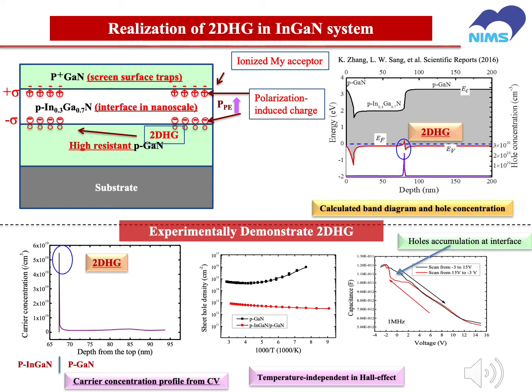But the two-dimensional electron gas is already utilized for HEMT device applications. The two-dimensional hole gas is very difficult to obtain. Here we use the InGaN/GaN heterojunction and successfully realized this two-dimensional hole gas from the band bending. From the CV characteristic, we estimate the carrier concentration dependent on the depth, and clearly we observed the hole accumulation at the InGaN/GaN heterojunction. Also from the temperature dependent Hall effect measurement, we confirmed the existence of the two-dimensional hole gas.